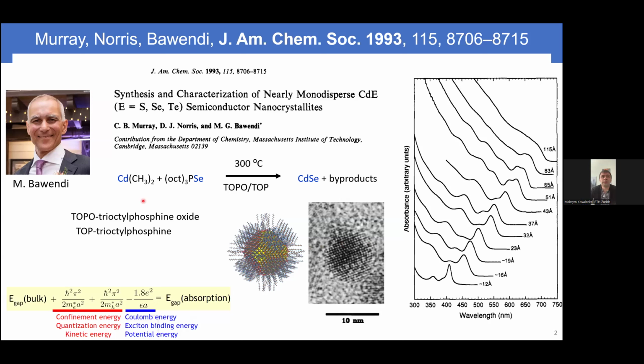Because of that high temperature method and these ligands, they could control the mean particle size very precisely with very narrow size dispersion, so that you eventually reach molecular-like absorption features and in many ways behavior. So highly confined quantum dots. And so the HOMO-LUMO gap, or the bulk band gap of these semiconductors, is then scaling with the dimension if you go strongly below a certain dimension. Now, this was well before I studied chemistry, and I studied chemistry myself a bit later.